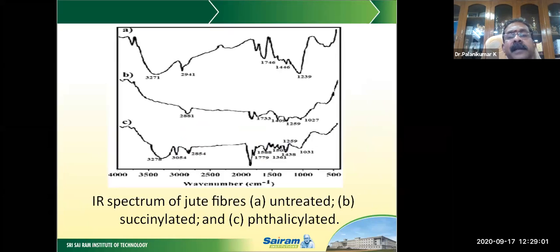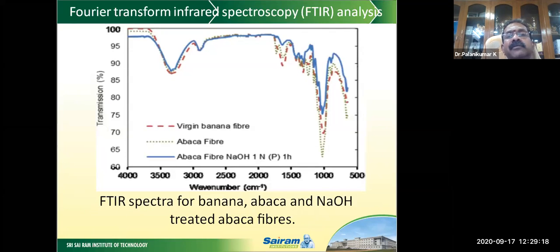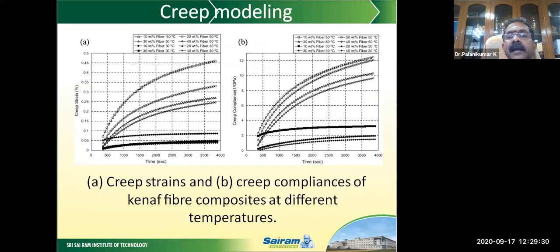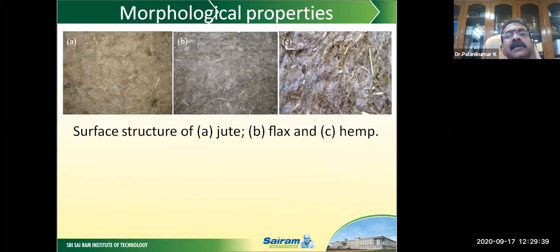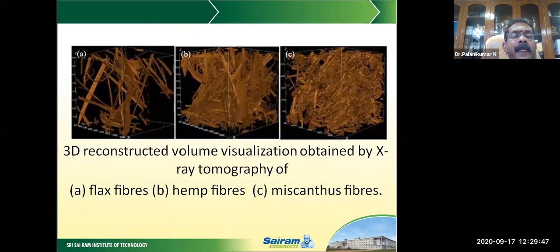This is the IR spectrum obtained for jute fiber: A untreated, B succinylated, and C phthalylated. This is the FTIR, Fourier transform infrared spectroscopy analysis obtained for banana, abaca, and NaOH treated abaca fiber. So this is a creep strain and creep compliance of kenaf fiber composite at different temperatures. So this is the morphological property or surface property. So this is the surface structure obtained for jute, flax, and hemp. This is the 3D reconstructed volume visualization obtained by X-ray tomography of A flax fiber, B hemp fiber, and C miscanthus fiber.